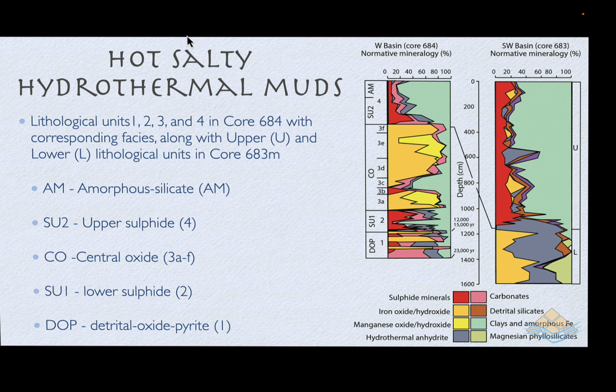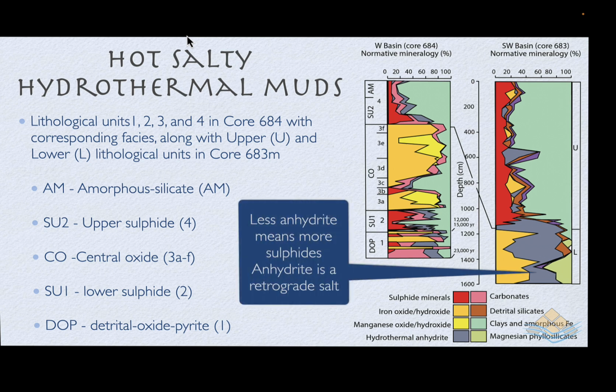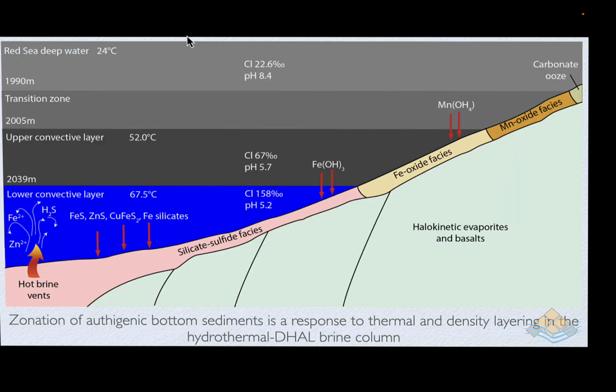What's also interesting here is that where we have lesser amounts of anhydrite, we have more sulphides. And that's reflective of the fact, as we'll discuss shortly, that anhydrite is a retrograde salt. It becomes less soluble as the temperature increases, which is the opposite of most of the other phases we're considering. So if we look at it in terms of the density stratification in the brine column, there's 1990 as our onset transition coming out of the normal Red Sea deep waters at about 24 degrees.